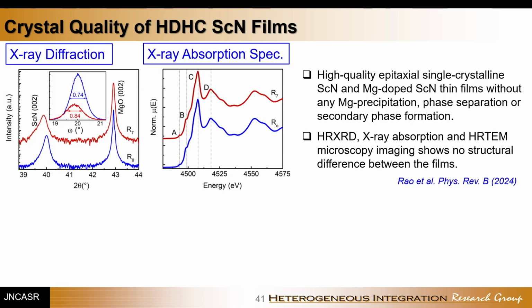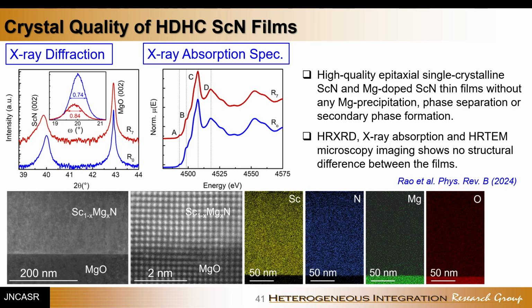And the important point is that all of this happens while the material is still a single crystal, because you are not introducing any geometric defect, which is a precursor for Anderson localization. What we are doing is basically changing the potential fluctuation by changing 3+ with 2+, and this is also supported by transmission electron microscopy showing the perfectly epitaxial single crystal nature. So, one last slide before I end.